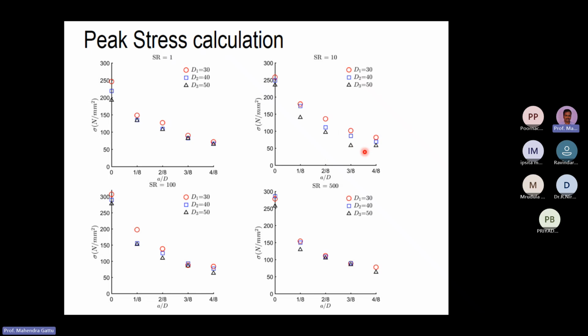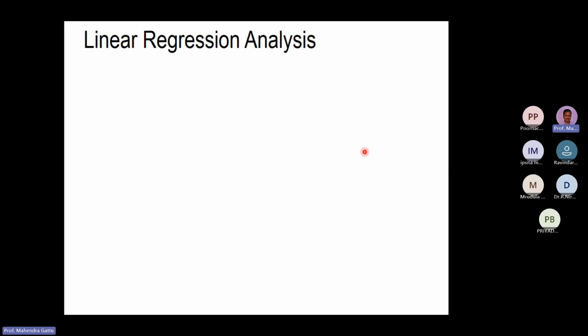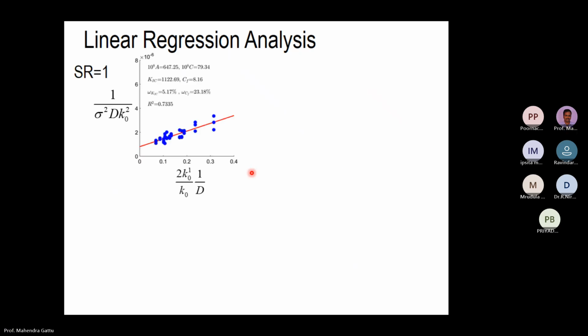Okay, so with this we are sure that there is some size effect, and this composite will follow quasi-brittle fracture mechanics criteria. So we do our linear regression analysis using that equation. I'm plotting 1 by sigma square D against the K naught square and 2 K naught prime by K naught, 1 by D. I'm using the linear regression tool, and I'm plotting it here. So this trend I'm getting, and I can fit a straight line y is equal to mx plus c. So from the intercept and from the slope, we can find out our KIC and CF values.